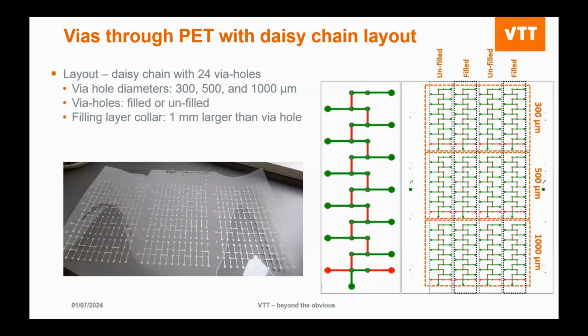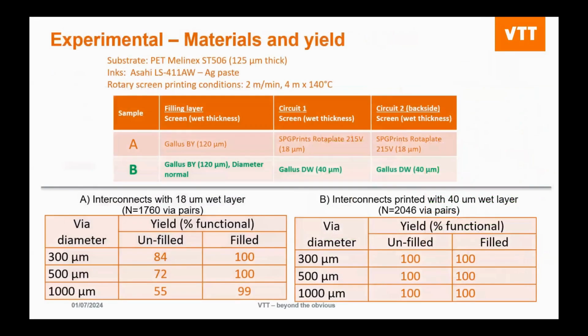The cross direction is 30 centimeters. In the machine direction, the repeat length is 40 centimeters. And we did different sized via openings. In this study, we used this Melinex ST506, a particular high-grade polyethylene terephthalate. The ink we were using was this Asahi 411AW, and then there are the characteristics of the printing run.